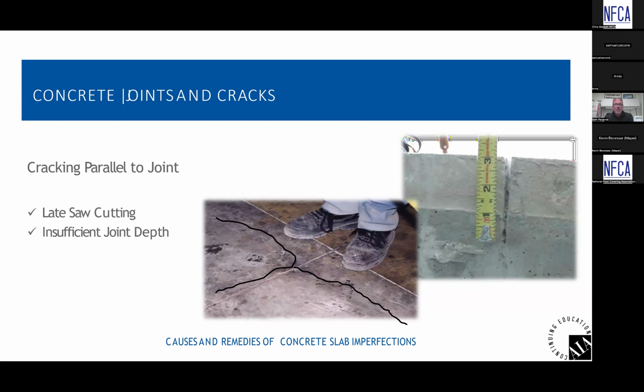So, couple of pictures here. Late saw cutting could be an issue. We talked about cracking in concrete due to the shrinkage of concrete, and those control joints that are cut are typically done on day one. Once the concrete has been screeded, floated, and finished, they come back and cut those joints. What happened in the left picture here is a joint that was cut too late and the concrete had already cracked.